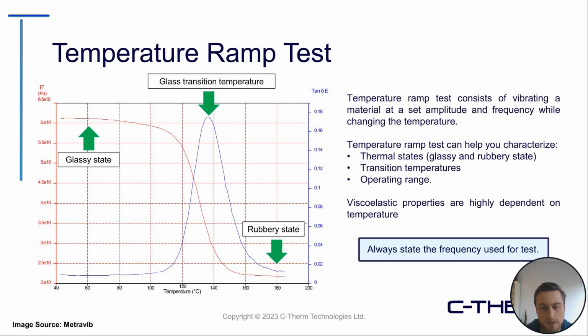The temperature ramp test is the bread and butter when it comes to DMA, which consists of vibrating a material at a set amplitude and frequency while changing the temperature. This allows you to characterize thermal states, like the glassy state shown here, where a material is hard and brittle, and the rubbery state, where it starts to act more viscous. The transition temperature, like the glass transition temperature highlighted here, is indicated by the peak in the tangent delta, or loss factor. There are other ways to measure the glass transition temperature, but this is how we'll use it in this presentation. You can also identify the operating range—where the material properties are consistent and don't change too much.